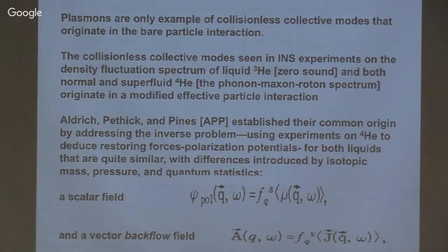Okay, thank you. Okay, so plasmons are not the only example of collisionless collective modes. All of the modes you see in the helium liquids have the same basic origin, but can't be dealt with by the bare interaction. The bare interaction gets modified, which is a very strong short-range repulsion, the long-range attraction is modified in the liquid. And we figured out a way to describe that modification and introduce the kinds of restoring forces that by then it was clear you needed for the helium liquids. You needed both the scalar field and the backflow field introduced by Richard Feynman.